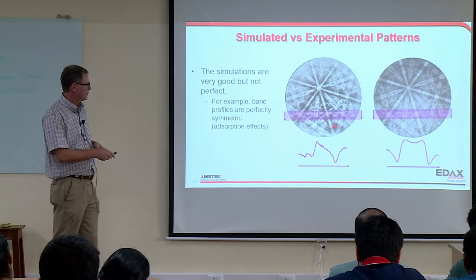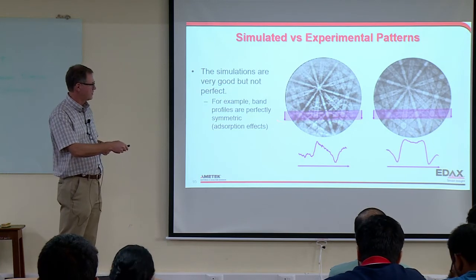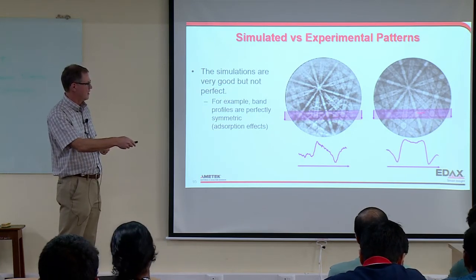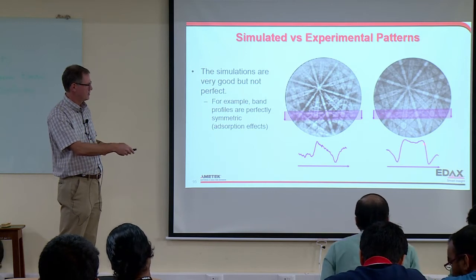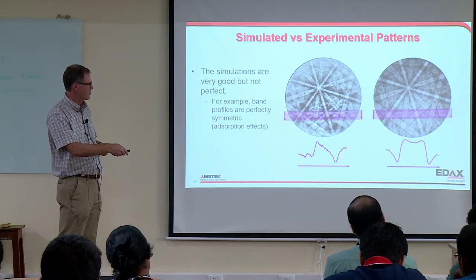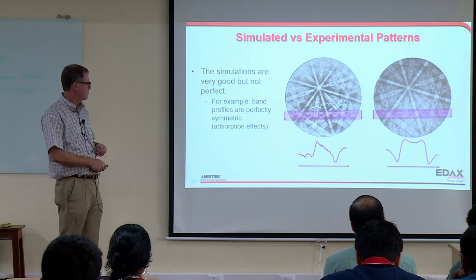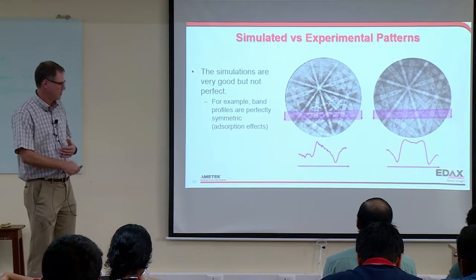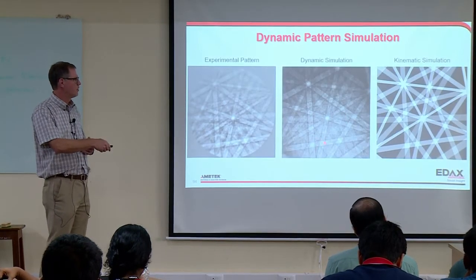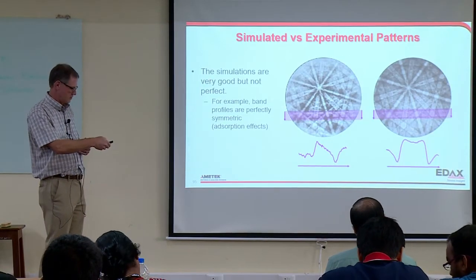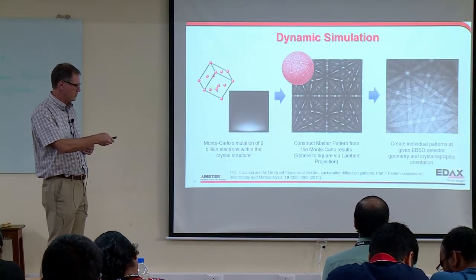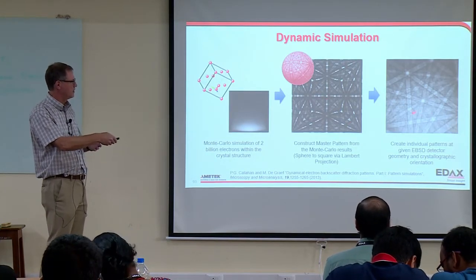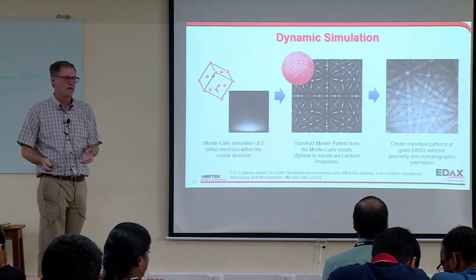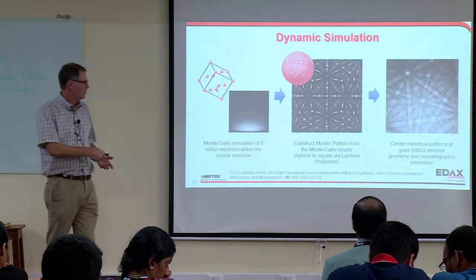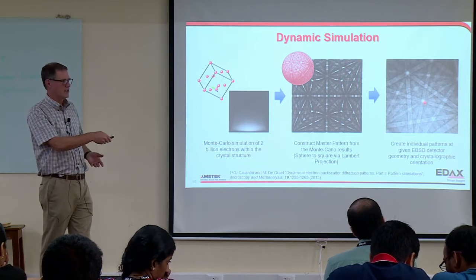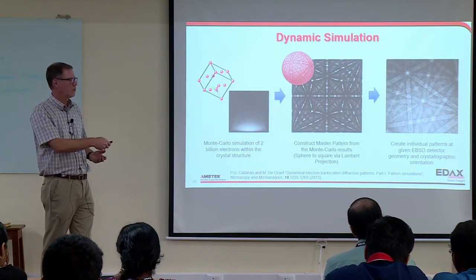We know they're not perfect. For example, look at the intensity profile across this experimental band versus this band in a simulated pattern. It's nice and symmetric here. It bounces around a lot more here. We know this has to do with absorption, and we could account for this, but it means we couldn't use this master pattern approach. We'd actually have to calculate this from first principles every single time. And that's an advantage of this master pattern: this takes hours, this takes milliseconds, microseconds. It's really quick.